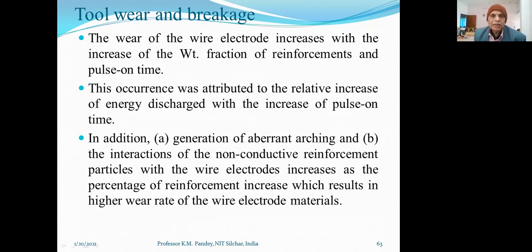we have studied that the wear of the wire electrode increases with the increase of the weight fraction of reinforcement and pulse on time. This occurrence was attributed to the relative increase of energy discharge with the increase of pulse on time. In addition, with the generation of aberrant arcing, the interaction of the non-conductive reinforcement particles with the wire electrode increases as the percentage of reinforcement increases, which results in a higher wear rate of the wire electrode material.